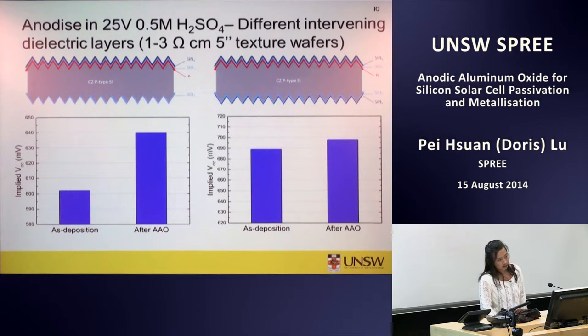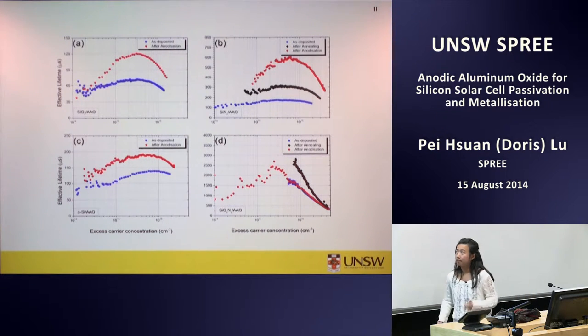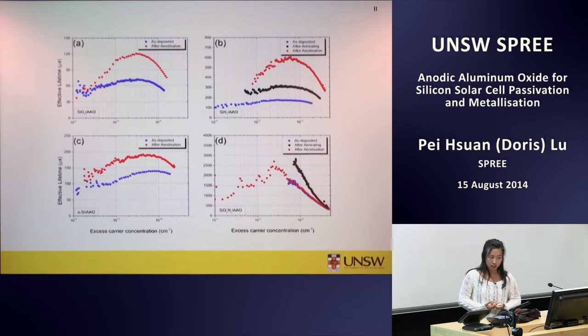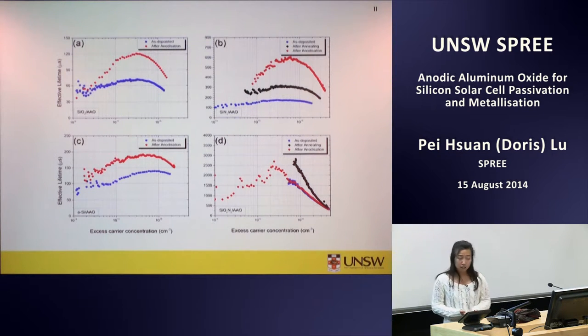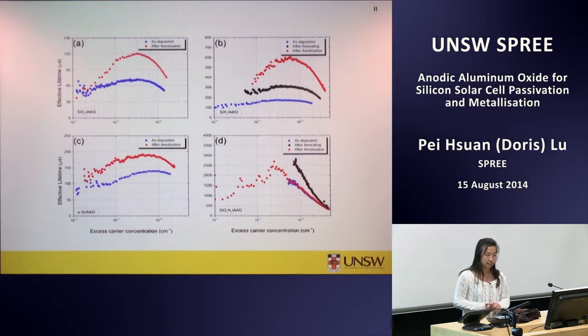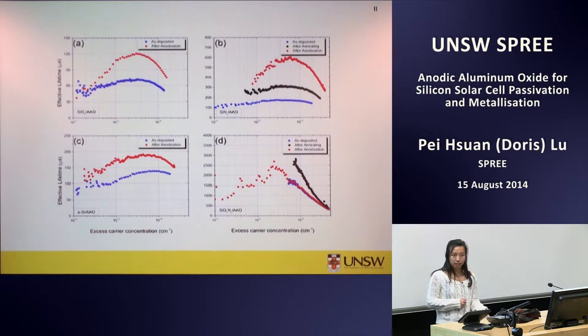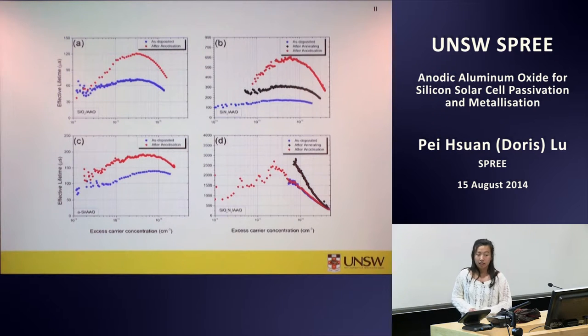So this promising result made me try to see if anodizing a layer of aluminium on other materials will give us the same result. So I tried to anodize on amorphous silicon oxynitride. It's interesting, anodizing a layer of aluminium on top of silicon dioxide, silicon nitride, amorphous silicon improves the effective lifetime across the whole injection level, except for silicon oxynitride. Anodizing a layer of aluminium on top of silicon oxynitride, there isn't a significant improvement in terms of effective lifetime and implied VOC.